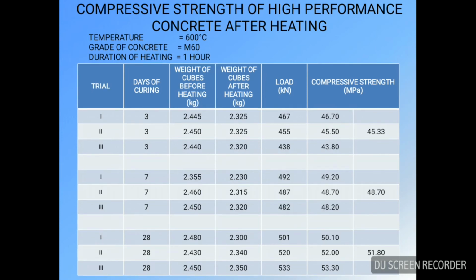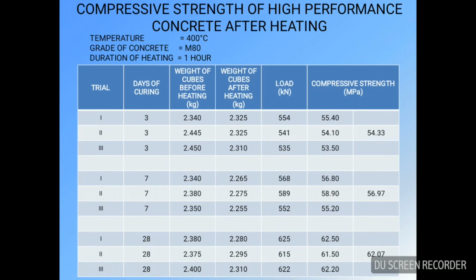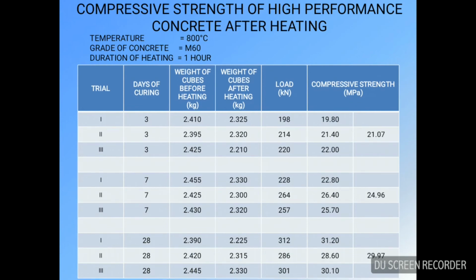For M60 grade of concrete at 600 degrees Celsius for a heating duration of 1 hour, the strength came around to be 45.33 after 3 days of curing, 48.7 after 7 days, and 51.8 after 28 days, which was about 73% of the strength. For M60 at 800 degrees Celsius, the strength again had a major drawback, as it came around to be 21 after 3 days of curing, 24.96 after 7 days of curing, and 29.97 after 28 days of curing.